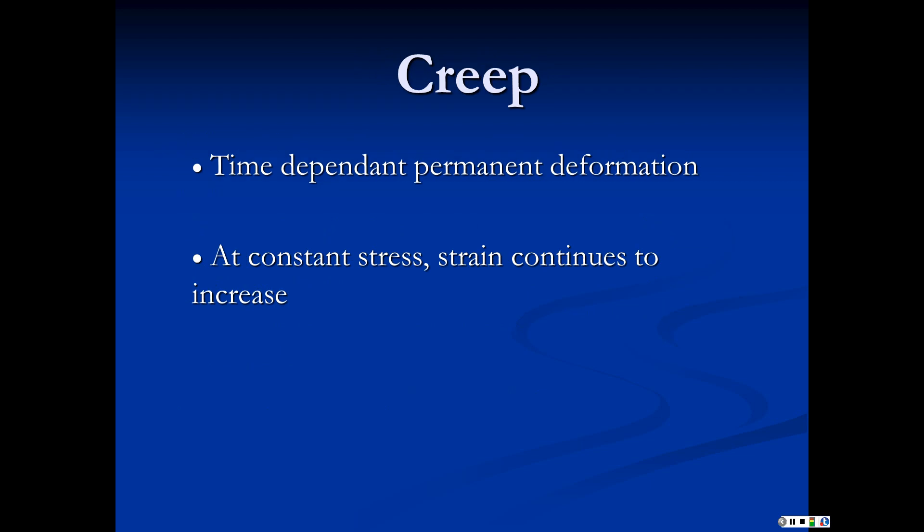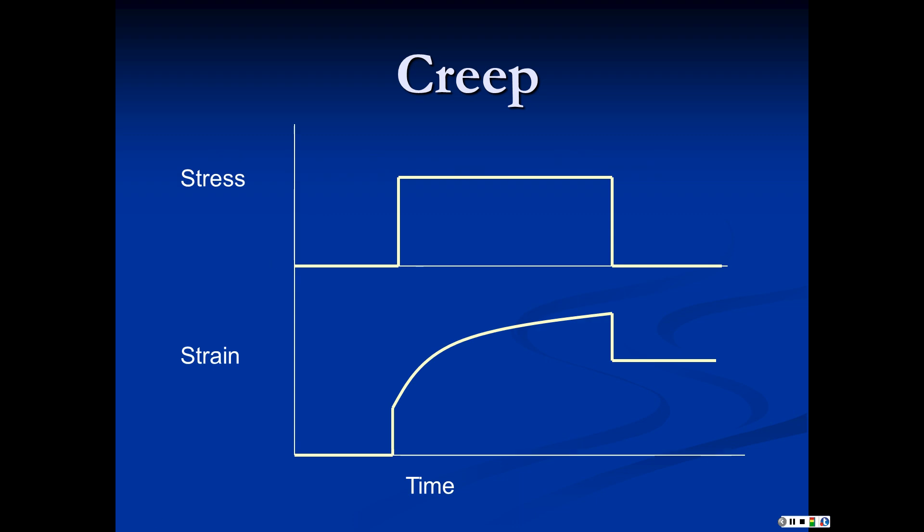So what is creep? It's simply time dependent permanent deformation. The idea is at a constant stress, strain continues to increase. Strain is not at rest as it does in elastic deformation. We apply stress, you get a strain level and then no more. If you look at this schematically, we apply a step function stress and hold that over time. We see no strain until we apply the stress. We get an instantaneous elastic strain, and then over time the strain grows and continues to grow. When I remove the stress, we remove the elastic strain and we're left with a permanent strain, which is the plastic creep strain. We'll play with silly putty and you'll see that in class.